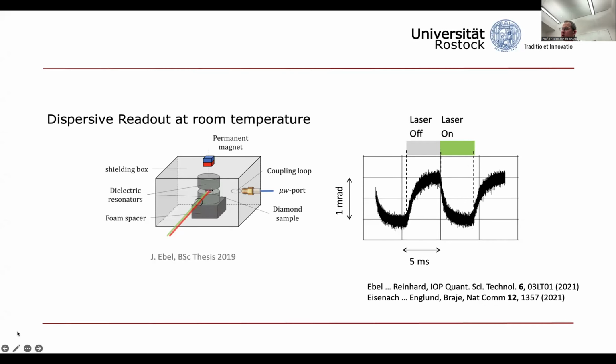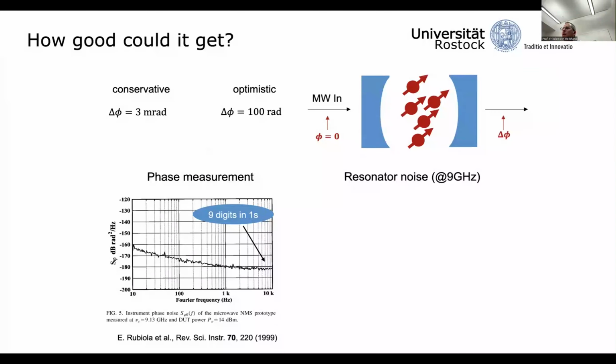So we have an NV doped ensemble sensor in a dielectric microwave resonator, excite this with a microwave antenna, and then repeatedly polarize and depolarize the NV centers to induce a spin signal. And indeed, we can read this from the microwave phase reflected from the resonator. Similar work has been done in the group of Dirk Englund, also achieving spin readout in such a device. Now, intriguingly, the performance of such a scheme could become rather good, because everything relies on a measurement of the phase of a microwave.